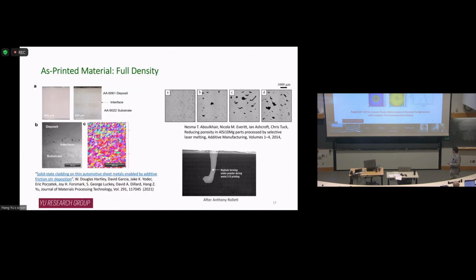What about the quality? Because we have intensive material flow, because we have compression and shear force there, essentially what we get in the as-printed state is a fully dense material. So there's no porosity. We don't have to worry about porosity in the bulk of the deposition. That is a big improvement compared to fusion-based processes, because you have solidification porosity, you have keyhole formation. So that's one unique advantage of this process: full density.